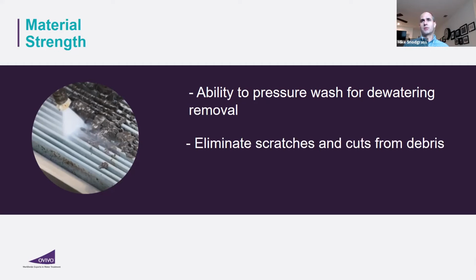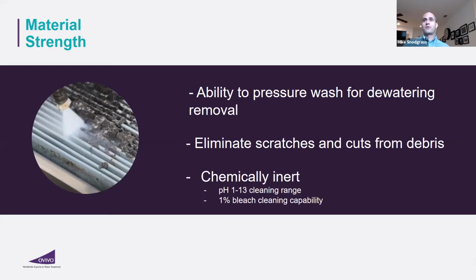Also, during normal operation, you're going to eliminate a lot of scratches and cuts from debris. Why that's important is that over the life of your membrane, your effluent quality is not going to be compromised, because you're not going to get pass through of solids or coliform material. That's because the integrity of the membrane is always maintained, because you're eliminating all these scratches and cuts that are very common in MBR applications. And it's a chemically inert material, so we can now clean much more aggressively, in terms of both types of chemicals as well as chemical concentration. What that allows us to do is, if you have an upset, you can hit it hard and hit it quickly, to not only ensure you get full recovery, but to do it quickly. So once again, it just opens up a whole new set of options for plants and plant operators.